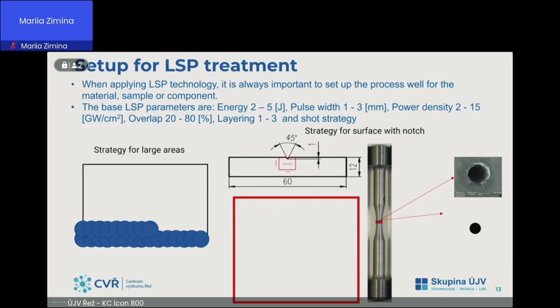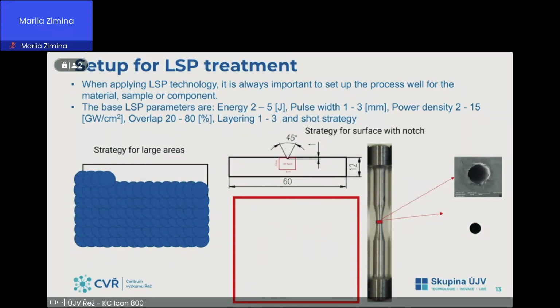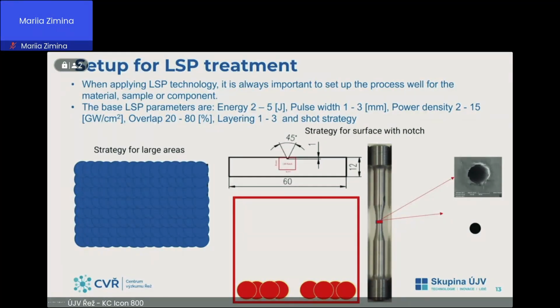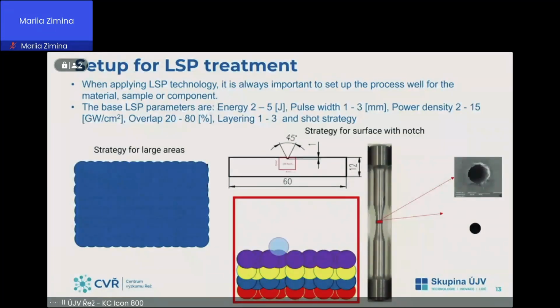Setup for LSP treatment is very important when we are applying LSP technology. It's always important to set up the process well for the material, sample or component. Shortly, when we use the LSP for some materials or component, we must know where is the critical area, where is the mechanism of degradation, is it fatigue or stress corrosion cracking, where is the problem, where is the location with maximum stress, and we must know maximum information about behavior of the material and properties, how the component is loaded and so on. Then we can modify LSP parameters for the application.